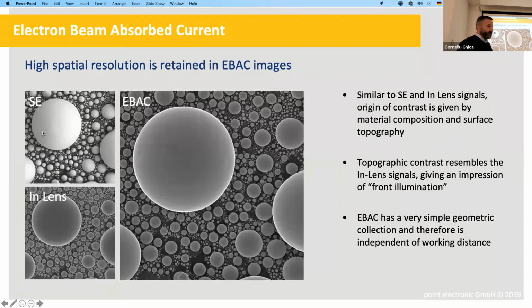You see the SE detector, because it sits on the side in the chamber, pulls electrons to one side, so we have this shadowing effect, which is great visually because it gives a very good impression of 3D. Whereas the in-lens detector looks straight onto the sample, more like a passport type of photo, like frontal illumination. And our EBAC is very much the same because there's no collection geometry. It's just the beam going to the sample, current being absorbed. We don't have to worry about where the detector sits. So this is EBAC.